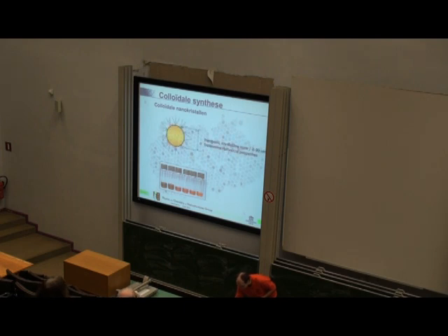And if you think in terms of categories, you have here the inorganic core. That's what we see with the TEM as well. And this actually determines the physical properties of these materials. Typical dimensions, 2 to 20 nanometer. And then this core is surrounded by these ligands, by these surfactants, and they form a kind of shell around this nanocrystal. Typically, we use pretty long-chained carboxylic acids, for instance, or phosphonic acids.